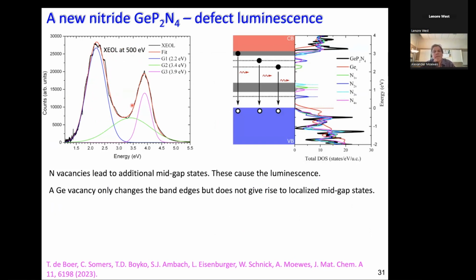It turns out, and this is something that Tristan has somewhat pioneered, this method, we now can do in our calculations, we can take out, for example, nitrogen or germanium atoms, so we create defects. And it turns out, and he has done this here on the right side in the calculation, there are 1, 2, 3, 4 non-equivalent nitrogen sites. He has taken in subsequent calculations always one of those sites out, and this gives rise to the spectra. The point is, I summarize it, when you take out a nitrogen atom in GeP2N4, it turns out that all these additional states here in the band gap shape up.